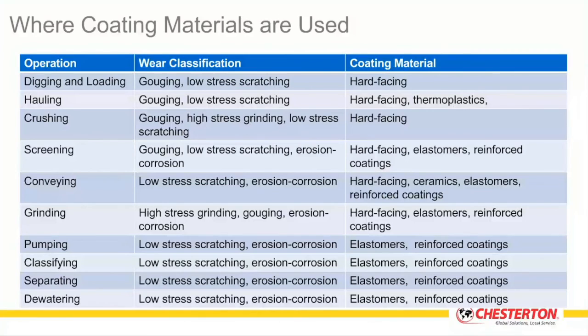But typically, in the front end, the process seems to be driven more by the hard-facing and thermal spray systems. And as you move to the back end, it tends to be more elastomers and reinforced coatings. That's based on wear resistance, chemical resistance, and the resistance to gouging wear, grinding wear, scratching wear, or erosion corrosion.